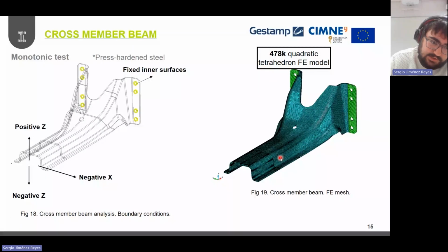And then finally, with regards to this cross-member beam demonstrator, which was manufactured by Gestamp, we studied here indeed several types of loading scenarios. The first one, monotonic test, and then we move to the fatigue test. So basically, in this monotonic scenario and also in the fatigue scenario, what we're doing is fixing these inner surfaces of the cross member beam while applying a monotonic increasing displacement in this final end of the demonstrator.